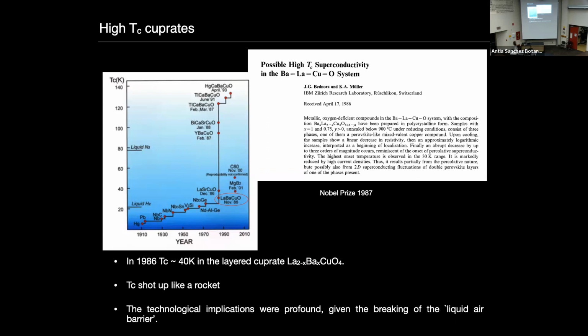Even more importantly, you can see that more and more cuprates were discovered very, very quickly with higher and higher critical temperatures. And among those, one discovery that was particularly important was that of this yttrium barium copper oxygen system, or YBCO, that is the one that I showed you before in the demo of the magnet levitating on top of a superconductor. The reason why the discovery of this was so important is because it was the first one whose Tc was above the boiling point of liquid nitrogen. And liquid helium, sorry, liquid hydrogen, is probably not a very cheap thing to do, but liquid nitrogen is not so expensive, probably the price of beer or milk, whatever you like best. So the technological implications of these were, of course, very profound.